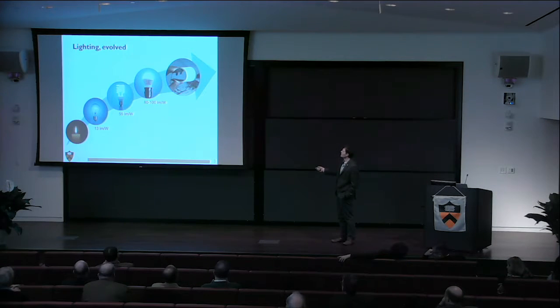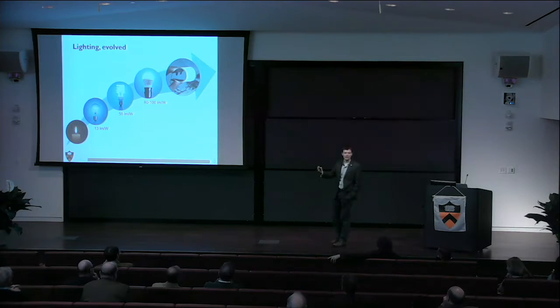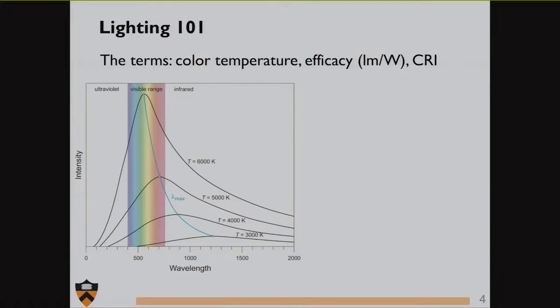Today's state-of-the-art is represented by solid-state light from gallium nitride-based LED sources. These have efficiencies of 80 to 100 lumens per watt. To put that in perspective, compact fluorescent sits around 55 lumens per watt. The standard incandescent tungsten filament sits at 13 lumens per watt.